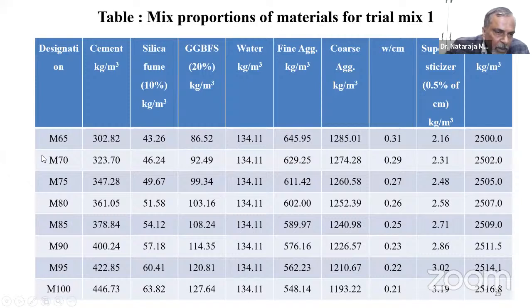And kindly see M65 going up to M100. The water cement ratio is 0.31 going down to 0.21. Getting a concrete at 0.31 water cement ratio, even with 0.5 water cement ratio, your concrete is not workable. How can your concrete be workable with 0.31? So that is where the use of superplasticizer, that new generation superplasticizer, comes into the picture. And as you decrease the water cement ratio, as the grade of the concrete increases up to M100, you need to use a slightly higher dosage of such hyperplasticizer being permitted by the latest code of practice.